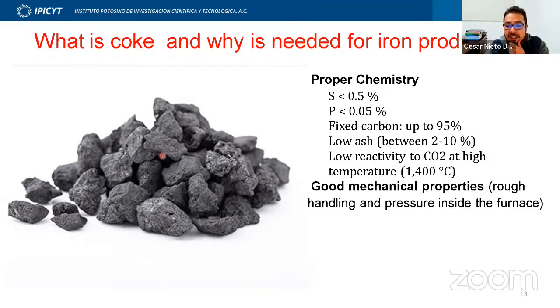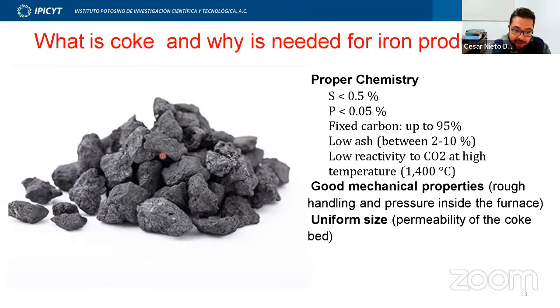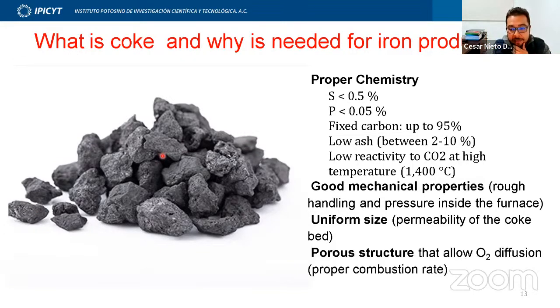Also, I already mentioned it has very good mechanical properties. It has very uniform size also, to allow all the iron that is melted in this furnace to pass through the coke bed. And also, the porous structure is very important in coke because these pores create a very high surface area, and at the bottom of the furnace, when the air is injected, the combustion happens very, very fast. That is very important.